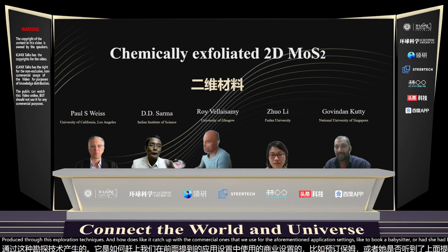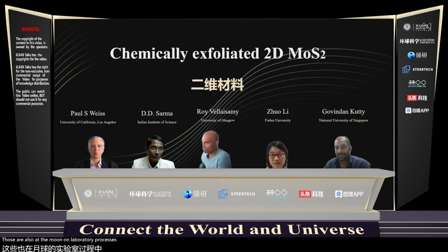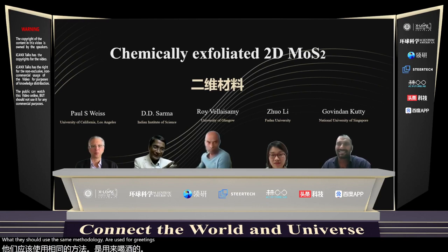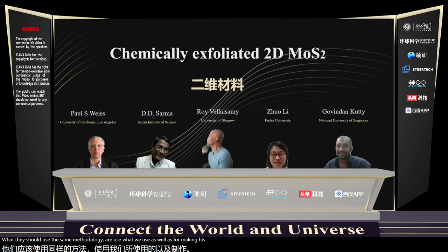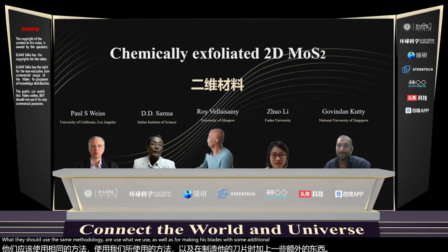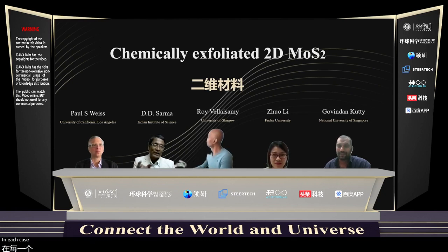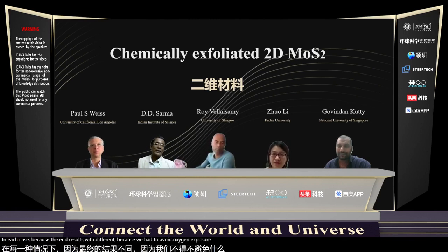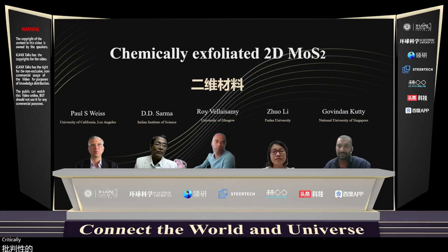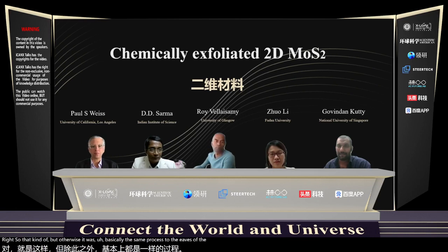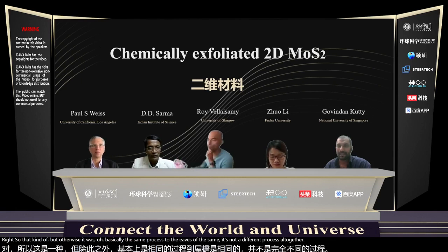Those are also at the moment laboratory processes. What I showed you is the same methodology I used for making a supercapacitor as well as for making these flakes, with some additional precautions in each case, because the end results were different. We had to avoid oxygen exposure, more critically when I want to do electron spectroscopy, because it's very surface sensitive. That kind of care. But otherwise, it was basically the same process. So the yields are the same. It's not a different process of chemical exfoliation that we used.